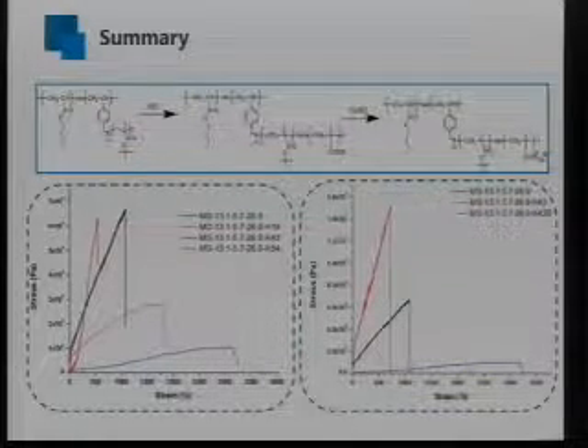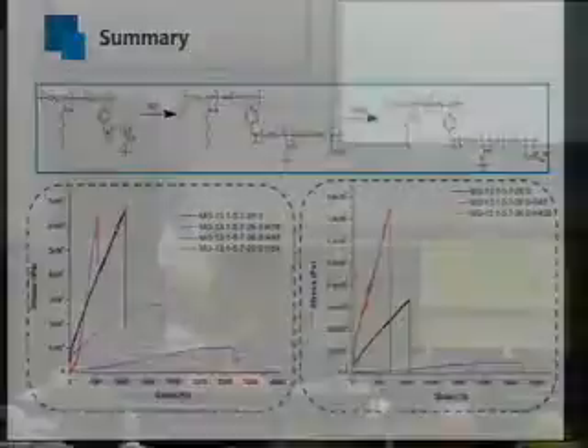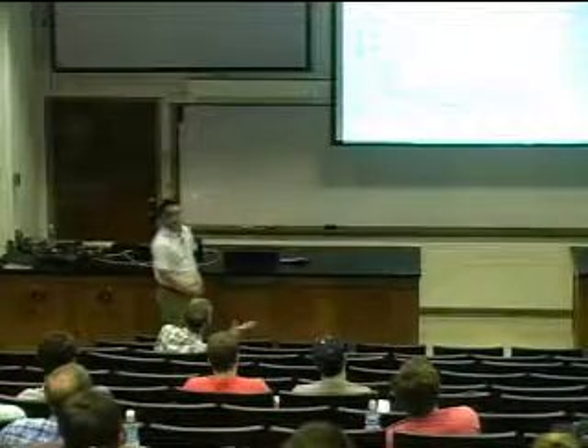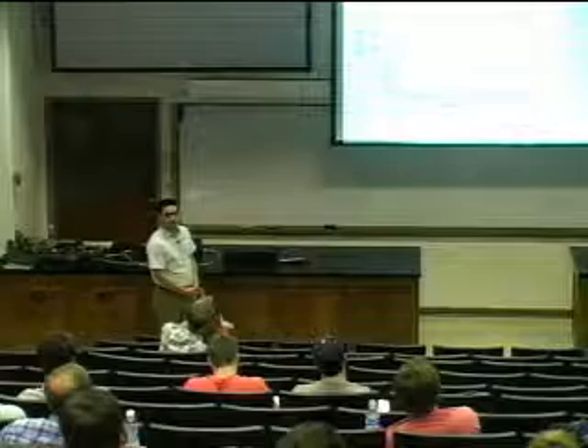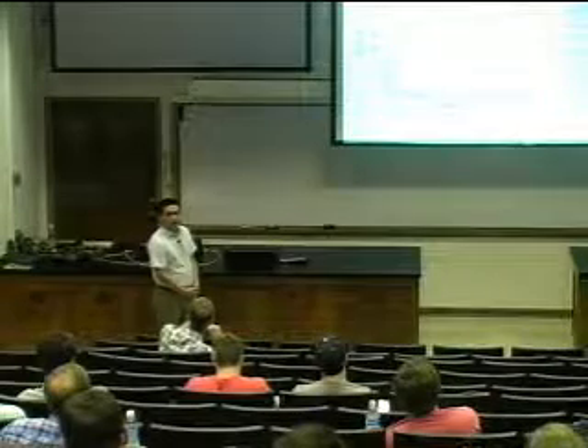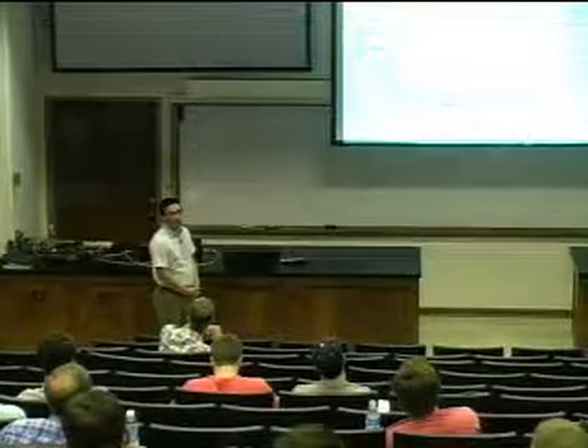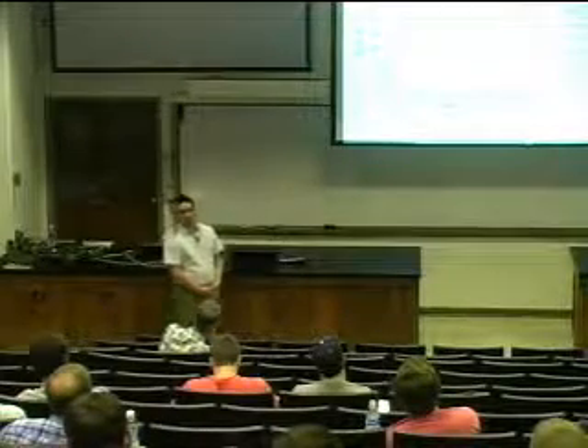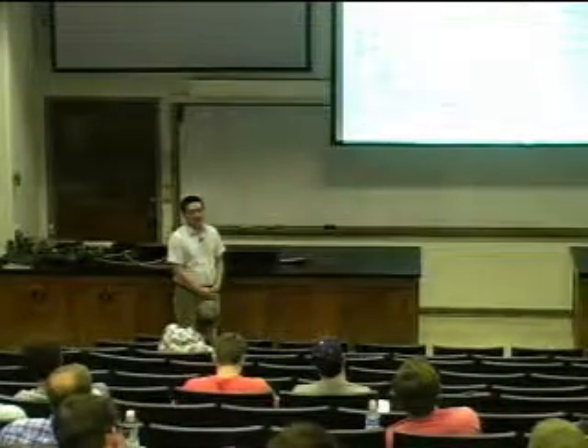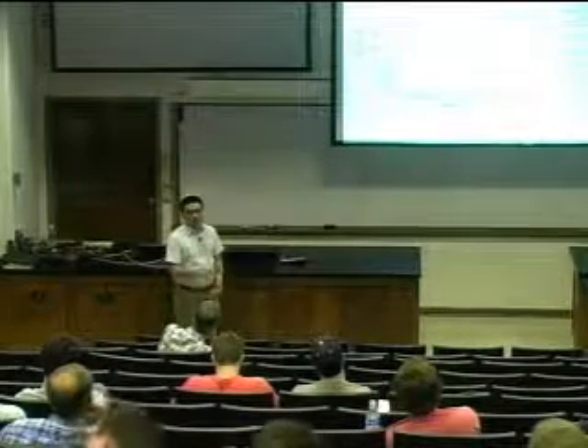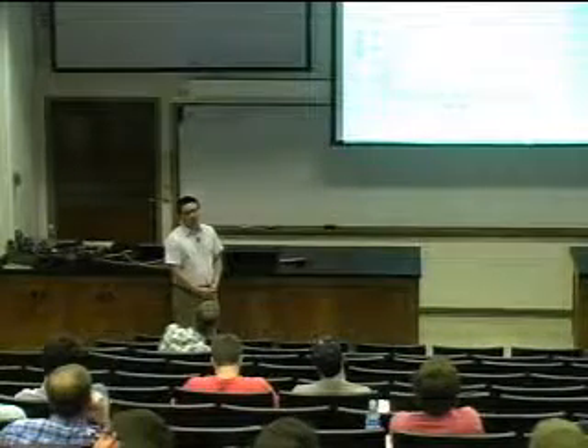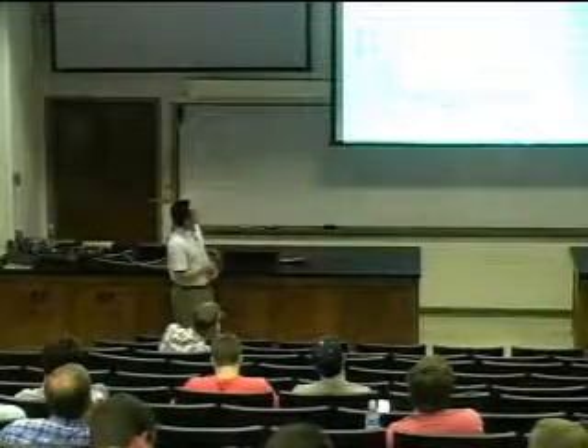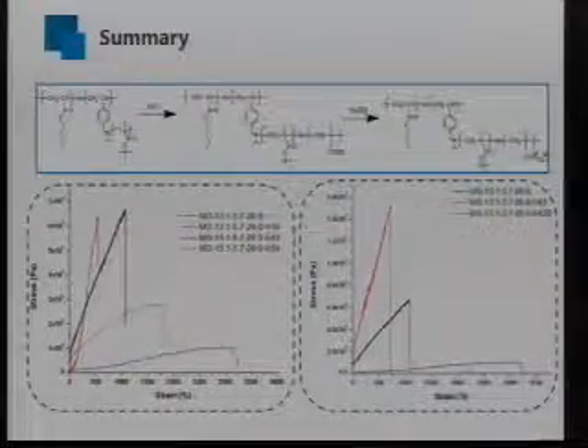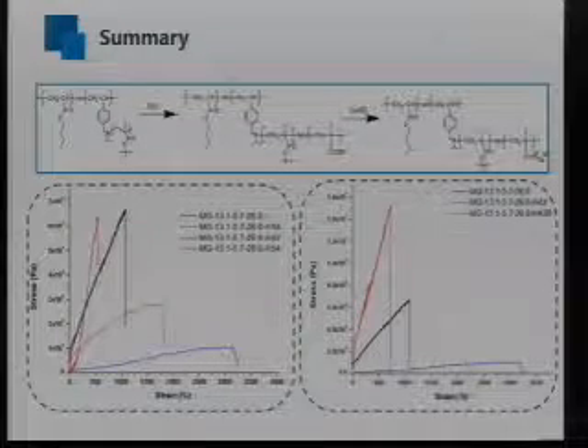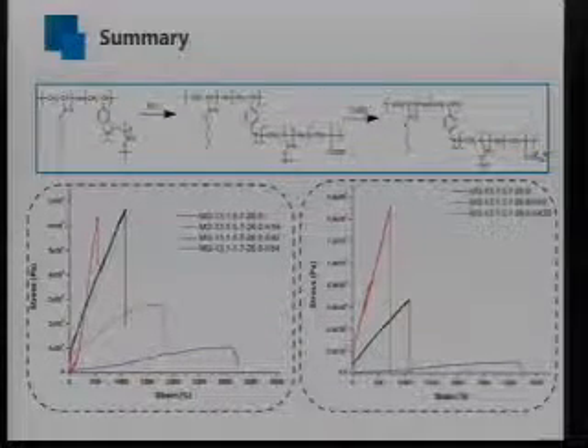And in the hydrolysis, you have both butyl esters and also methyl esters? Yes. So you can selectively hydrolyze these? For the hydrolysis of polyacrylate or polymethacrylate, with different conditions, you can hydrolyze different kinds of these functional groups. With the acid condition, it mainly hydrolyzes this kind of butyl group. With the basic condition, it can hydrolyze this kind of primary carbon. And also PMMA can be hydrolyzed if you use some catalyst and basic condition.